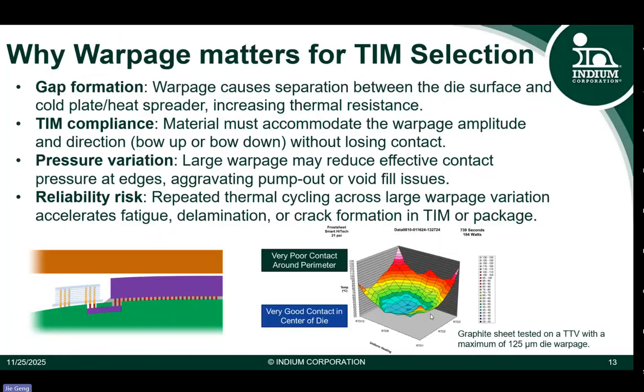So why do we need to consider warpage? First, because of warpage, a gap is formed, and also the warpage introduces a lot of thermal stress. So the TIM materials need to have the compliance to accommodate the warpage in both directions. You have to keep the contact at 2 interfaces. And also the TIM materials will be under thermal stress, which puts a challenge on the reliability. So the warpage makes the TIM applications very challenging.